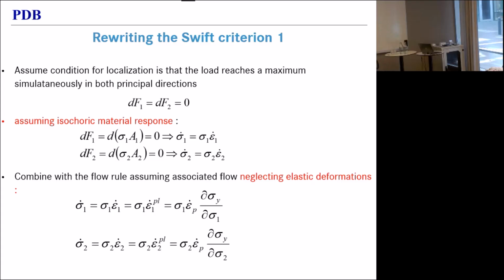Well, you work that out. You assume that your material response is isochoric, and your conditions translate in two differential equations for the stress rate in function of the stress and the strain rate in the corresponding direction. You then neglect the elastic deformations. You identify the total strain rate with plastic strain rate, and you replace the plastic strain rate by the flow rule, so by the equivalent plastic strain rate, and the derivative of the yield stress or the von Mises stress, you can use them interchangeably with respect to the corresponding principal stress component.